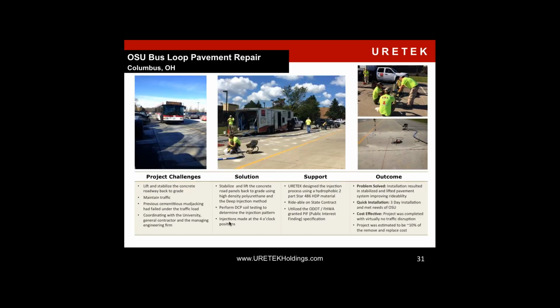The Ohio State University had a bus loop on one of their parking lots. They have 9-inch thick concrete panels, and they were all stair-stepped, if you will. All of them had some settlement, and the rideability was quite poor, and the panels were starting to fracture and have mid-panel breaks. So here, illustrating doing some soil testing prior to find out the soil strengths, doing dynamic cone penetrometer testing to verify that, and that helped design the injection pattern of the HDP material. You can see all the injection ports on those panels and injecting the HDP material while monitoring it and bringing them back up to grade.